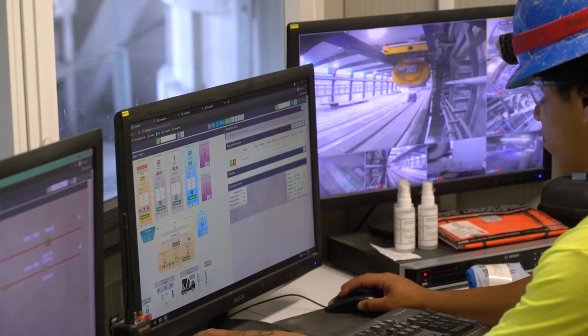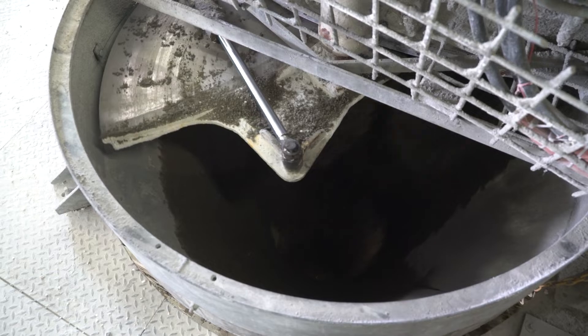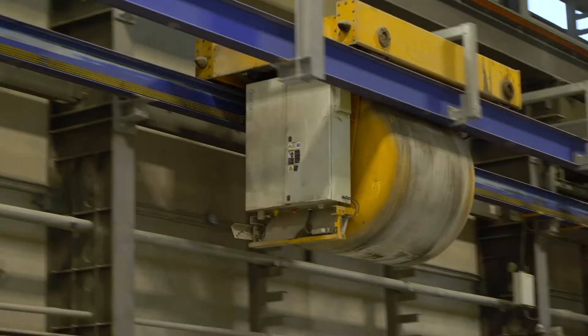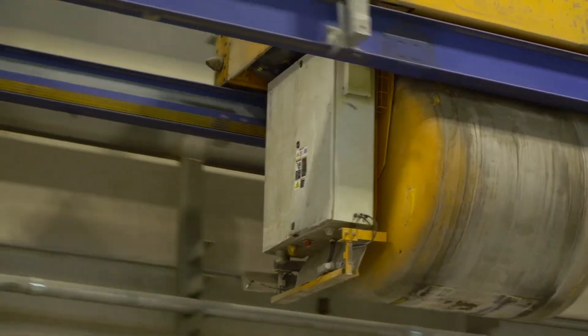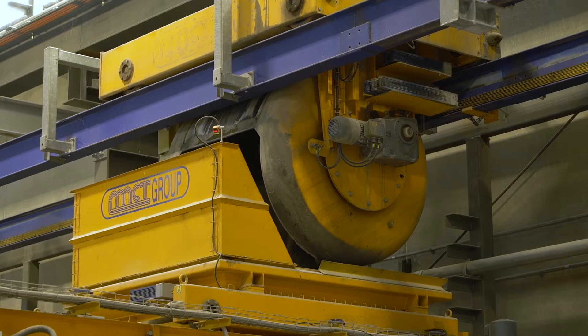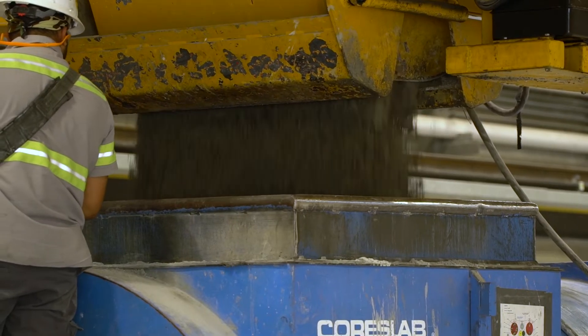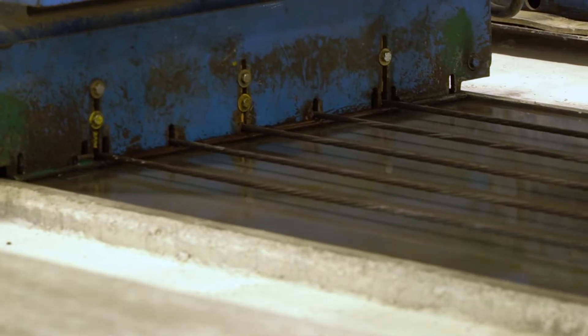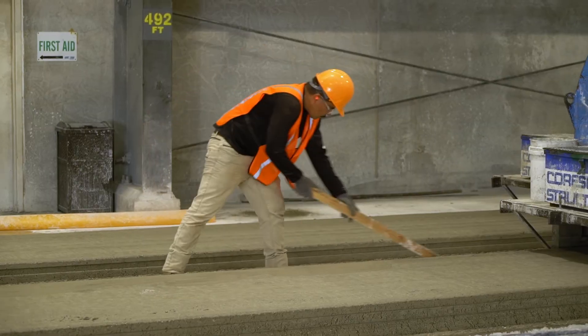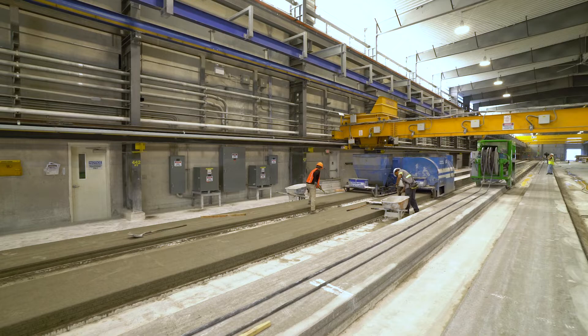Concrete is batched based on mix design provided by QC personnel. The dry mix concrete is discharged into an overhead conveyor system that delivers the mix to the hollow core machine on the casting bed. As the concrete falls into the hopper, multiple augers in high-frequency vibration compact the concrete and propel the machine forward, leaving a freshly made plank behind. Workers walk alongside the freshly cast product, cleaning edges and ensuring a quality finish.